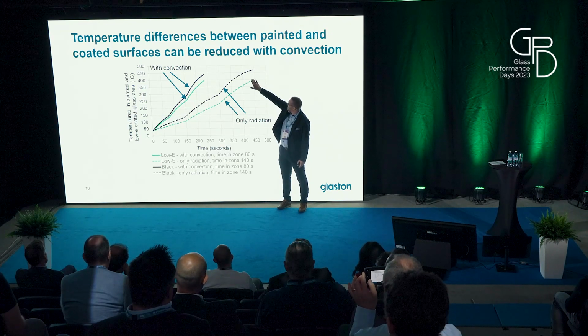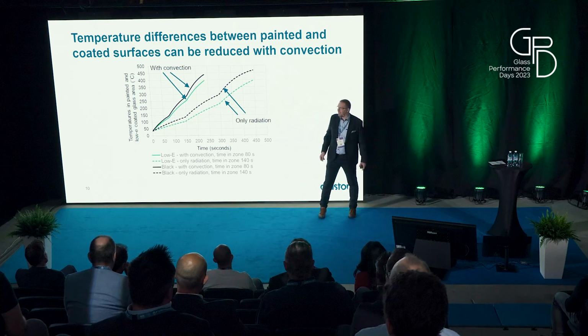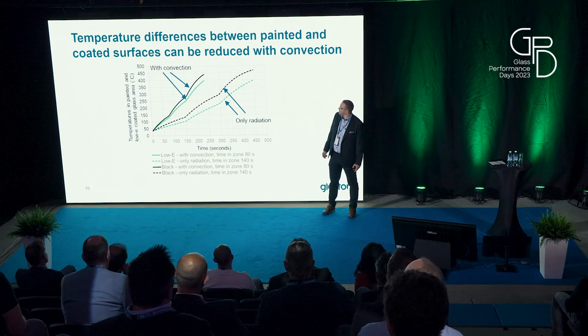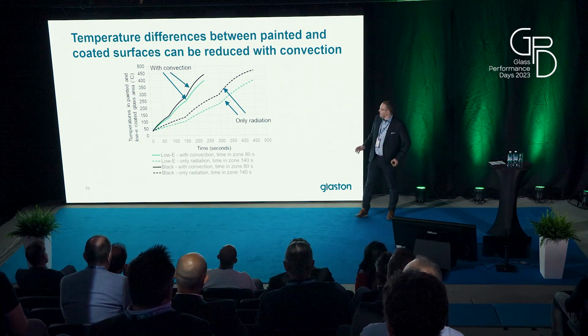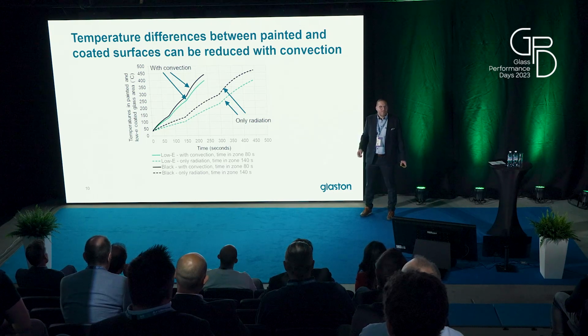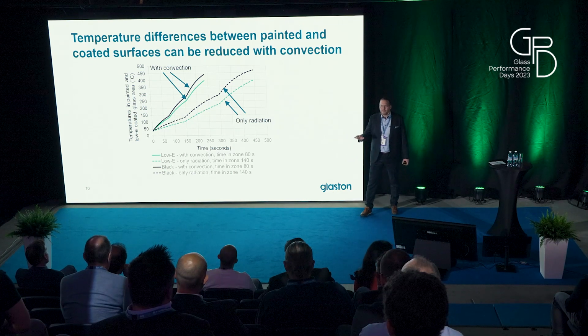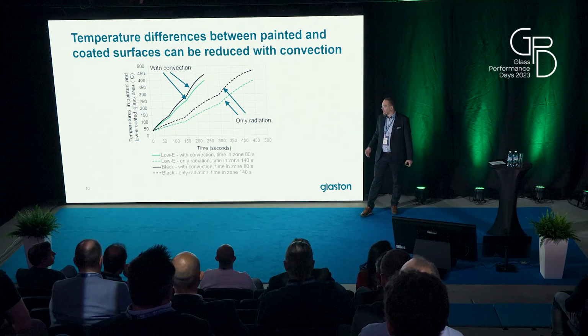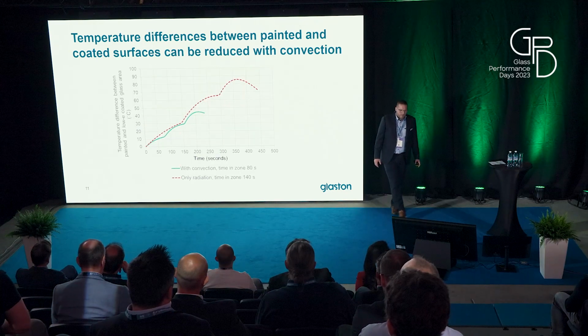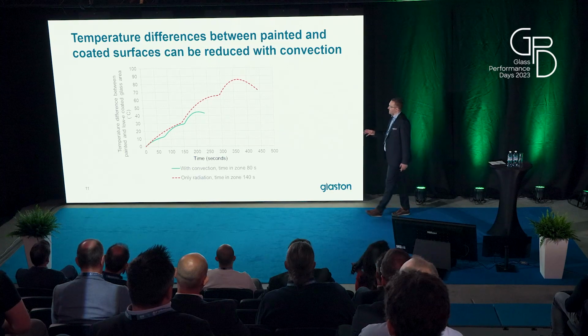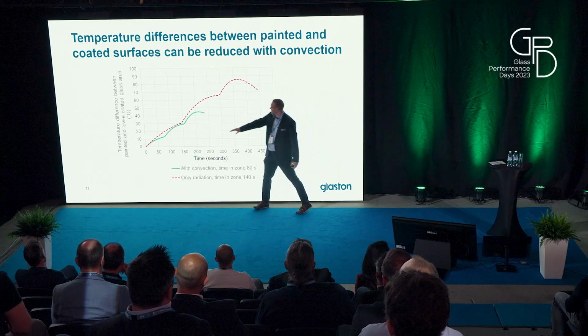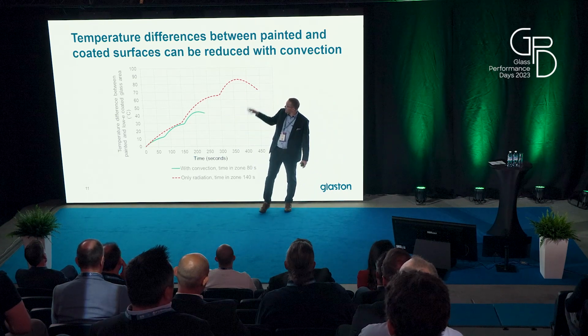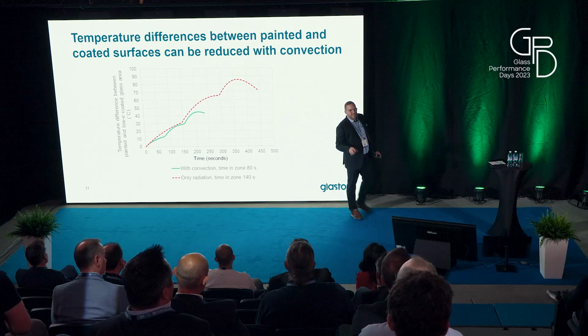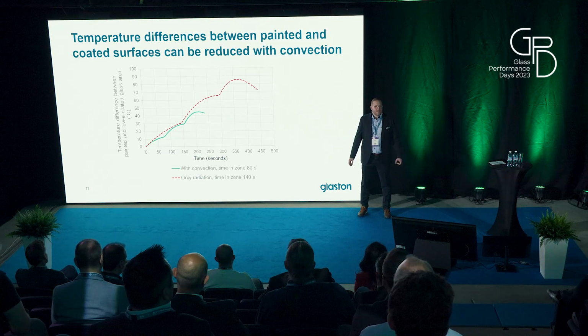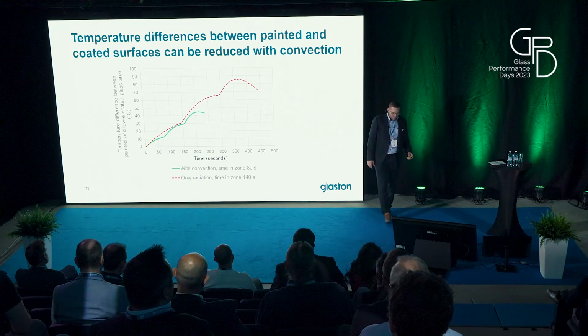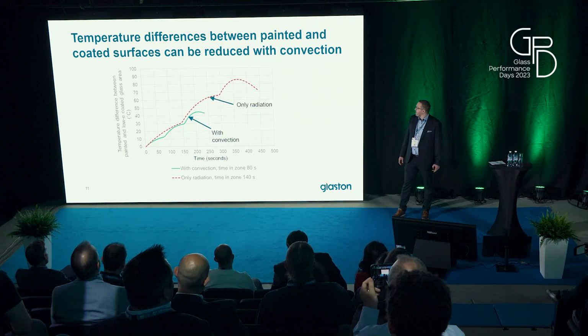Now at the end, when we have reached on the lower side the same temperature as with convection, the temperature difference is 60, 70 degrees. And we want that, as I said before, this temperature after preheating should be more uniform to get better end results after bending. So here are the same curves, or same results, so that you can see better what the difference is after heating, what this temperature difference is. So we can change from 70 degrees down to 40 degrees according to calculations.